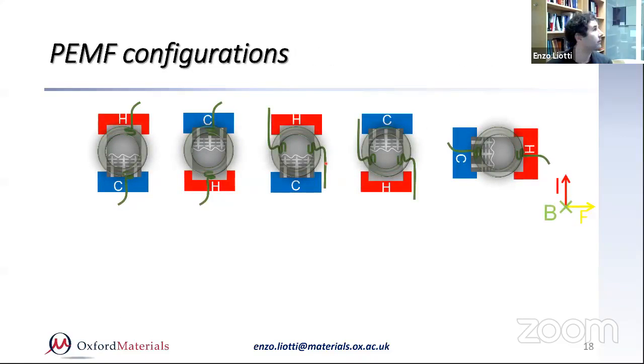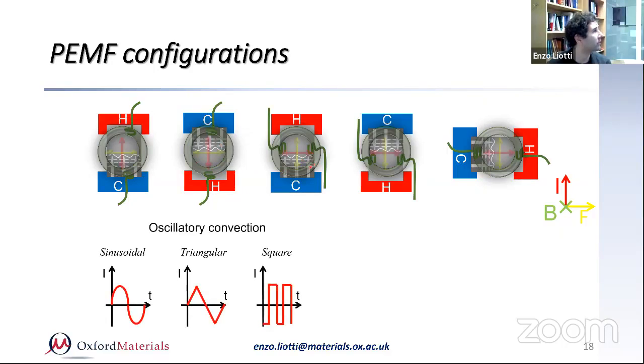So with our little rig, which I showed before, we could have several different setups. Because we can control the temperature of the two heaters, we can do the solidification from bottom to top or top to bottom. And by putting the wires in different locations, we can steer the liquid in different ways. If we put the wires at the top and at the bottom, then we steer the liquid horizontally compared to the growth direction of the dendrites. Otherwise, we can put the wires on the left and on the right and steer vertically, right?